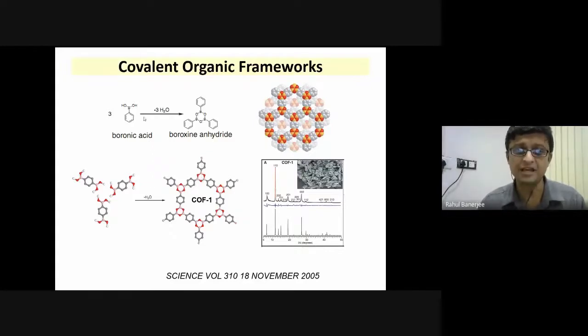So same, if you take a boronic acid and react it, you get this boroxine anhydride kind of structure. And if you take diboronic acid, you make this nice joint to joint, just with simple heating. Just do a simple heating, and you get these nice crystalline structures where there is no metal whatsoever, but they have a very nice framework structure. They are organic in nature. They are formed by covalent bonds.